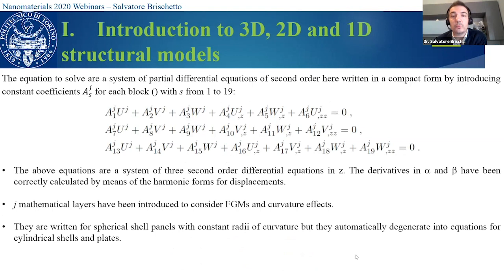So after all the substitutions, we obtain this final system, okay? This final system depends on j mathematical layers because in general, for each k physical layer, these coefficients are not constant because we have the dependence on the thickness coordinate and the curvature effects. But for example, if we also consider functionally graded materials, the elastic coefficients depend on z. So in general, these coefficients are not constant. But we need to have a system of partial differential equations in z with constant coefficients if we want to solve it. So we divide each k physical layer in several mathematical layers, and we can have constant coefficient equations. This system is a system of second-order differential equations in z.